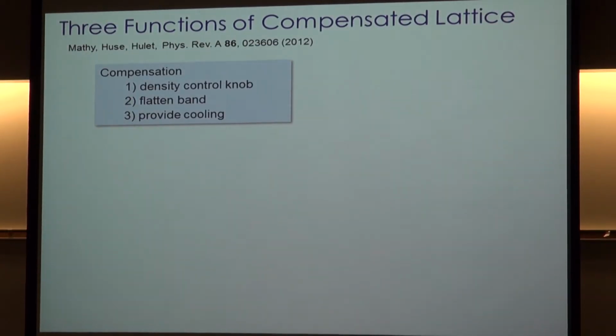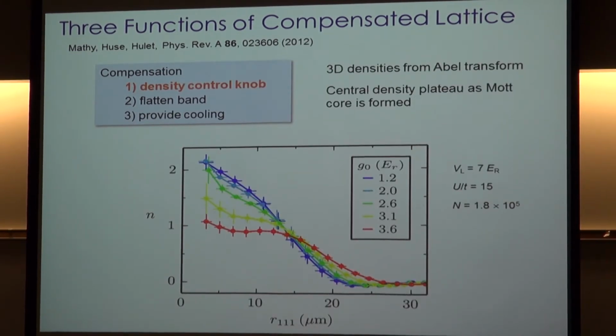It turned out there are some other advantages to the compensated lattice. There are three things that we've taken advantage of, one of which is the cooling, but two others. One is that it gives us a control knob on density. And the density, as you've seen, is very important to realize the Néel phase. You want a density of 1 atom per site. And also you can flatten the band, and I'll show that in a moment. You can take that harmonic potential and reduce its curvature, and so you don't have such an inhomogeneous system. And that's an advantage as well.